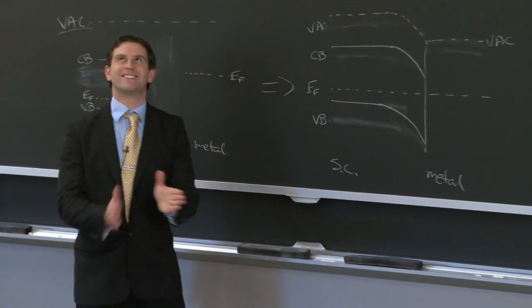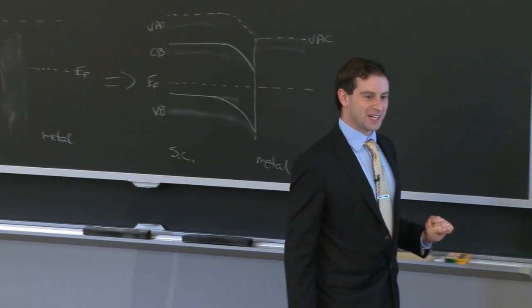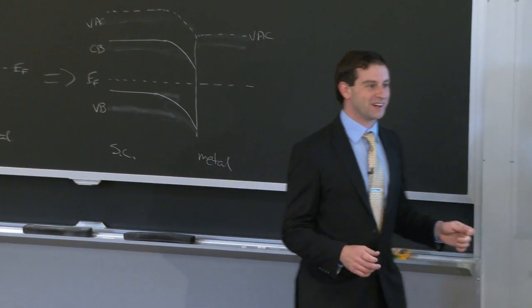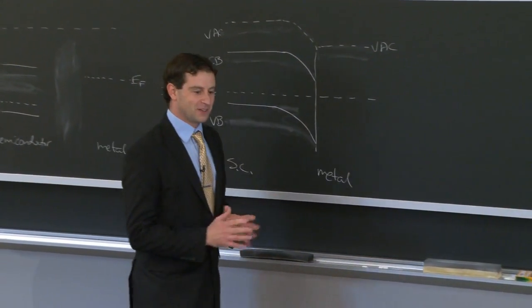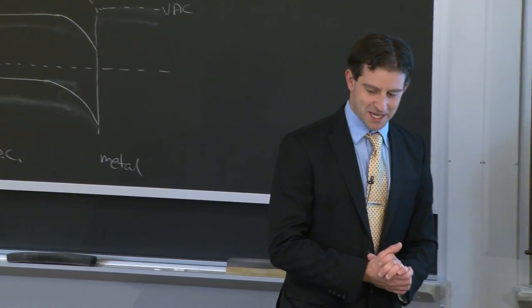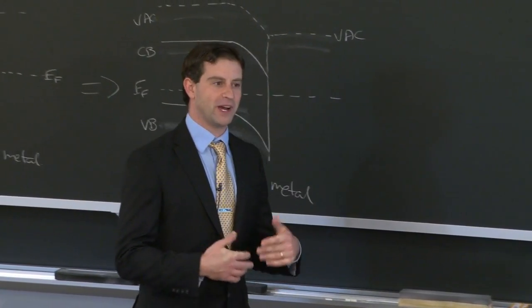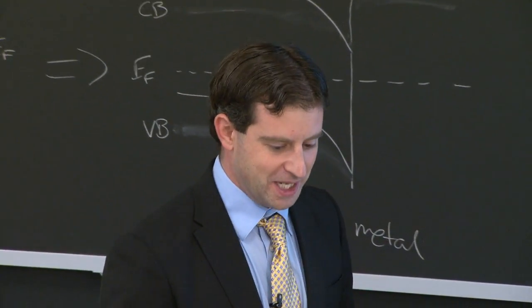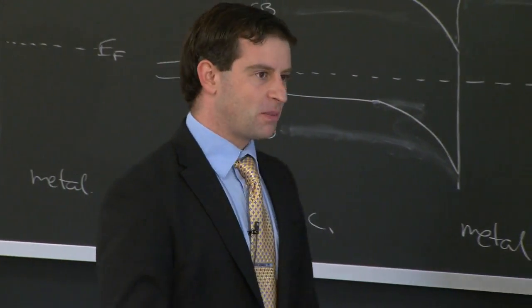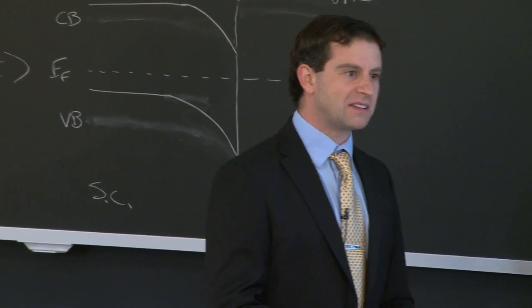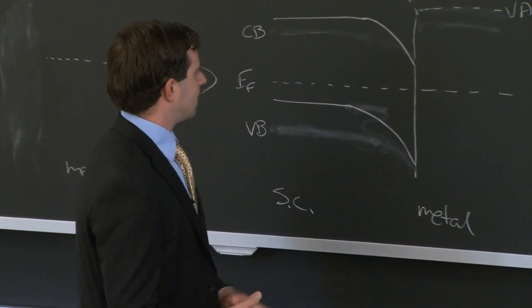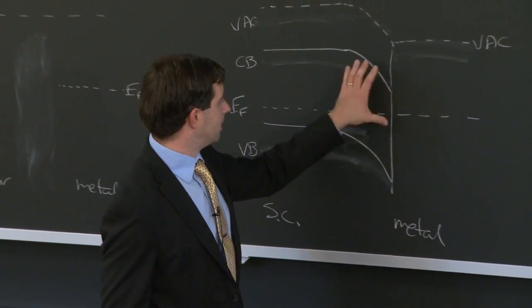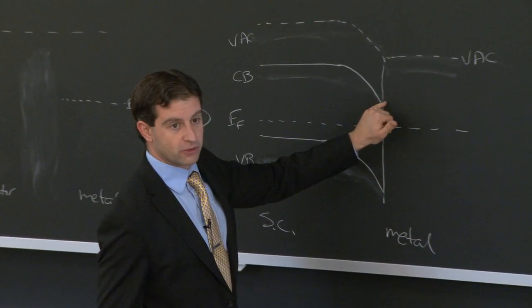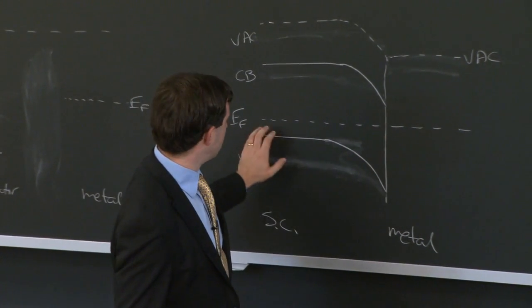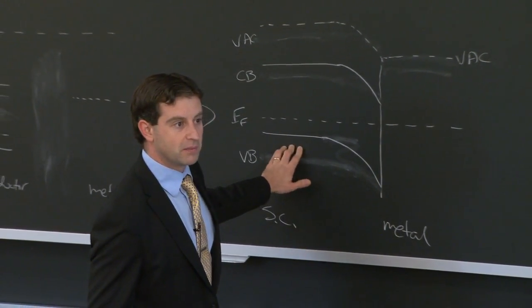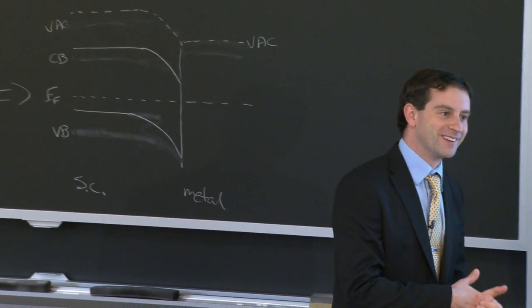Let me pause right here, because this is just utterly fascinating, and tell you the story about indium nitride. It's a common material that many people, I see a few knowing nods here in the audience. So indium nitride was a semiconducting material that people really didn't have a good handle on for a variety of reasons. And there was a renewed interest in it because people finally started to understand why the band gap was the way it was. And many groups started studying it. And they all started reporting this N-type indium nitride behavior, very highly doped N-type material. It turned out that there was this band bending here at the surface, and they were measuring a high electron concentration at the surface because of the bending of the bands. Whereas in reality, the intrinsic material deep within the bulk was P-type, but they just couldn't see it because their probes were touching the semiconductor at the surface.